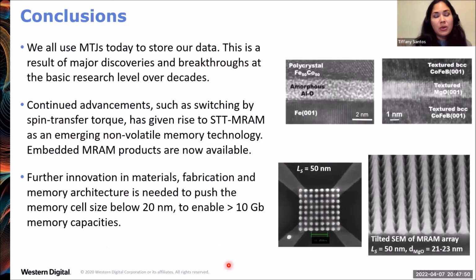So at this point, I want to conclude my talk. The message that I wanted to say in this lecture today is that we are all using magnetic tunnel junctions to store our data. And this has been the result of major discoveries and breakthroughs at the basic research level over decades, like the first experimental demonstration of spin polarized tunneling, and then much later, room temperature tunnel magnetoresistance for the first time, and so forth. And then advancements continued, such as the discovery of spin transfer torque, which allows us to switch without a magnetic field.